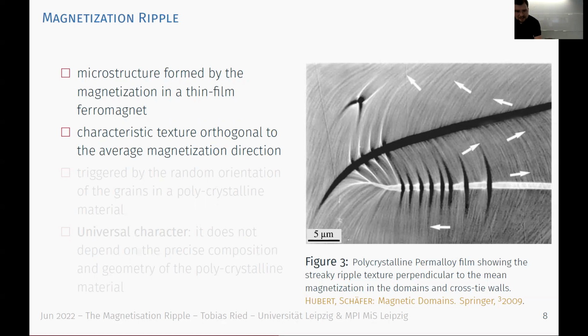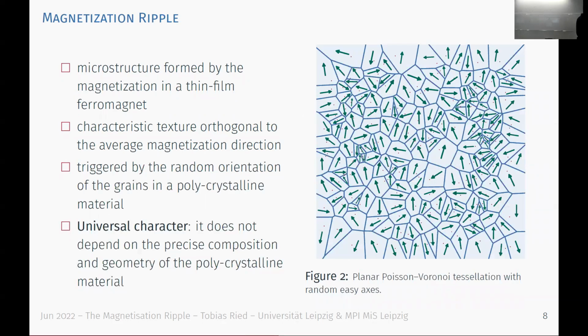And the whole thing is triggered by the polycrystallinity of the sample. So you can really think of your thin ferromagnet as being made out of small grains, and each grain carries, through the form structure of the grain, a preferred axis. So it carries its own easy axis. In order to model this stochastically, because we don't really know the process of manufacturing of this thin film, let's just assume we throw in some random i.i.d., or Poisson point process on the plane, do a Voronoi tessellation, and then throw in each of the cells a random vector, which describes the easy axis in this cell.